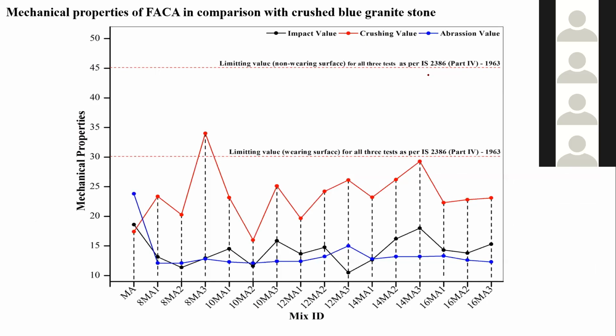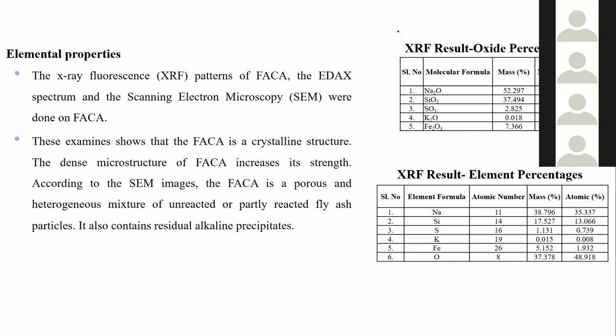Any aggregate that comes to the market, people ask whether it satisfies the code limits or not. So the limiting value for wearing surfaces is as per IS 2386 Part 4, 1963, for any aggregate we are using for wearing surfaces. Then the limiting value for non-wearing courses is as per IS 2386 Part 4, 1963. These graphs show mechanical properties like impact value, crushing value and abrasion value, as shown in the figure here. Most probably this aggregate is satisfying the mechanical properties.